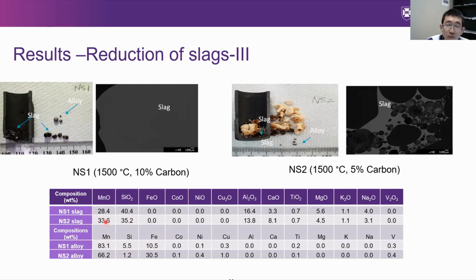However, when we see the composition of the slag, it also contains a high amount of manganese oxide. This is probably because the kinetics in our lab experiment is slow, with just 1 hour reduction. However, the industrial electric arc furnace provides good kinetics and can achieve a higher reduction of manganese oxide.